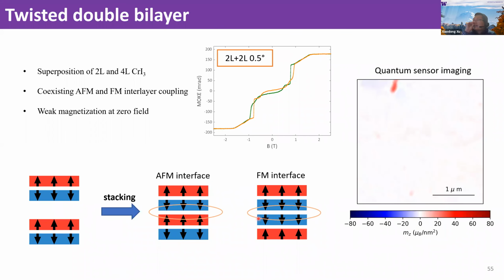The reason is that the bilayer is not ideal for studying this Moiré magnetism, because an individual bilayer is an antiferromagnet. If you put two bilayers on top of each other, it doesn't matter whether the interface is ferromagnetically or antiferromagnetically coupled, because you put a zero on top of a zero. So the net magnetization is always zero. That's why the bilayer is not ideal for studying this twisted magnetism. For example, we also used this quantum sensor to image this twisted bilayer. You pretty much just see nothing.